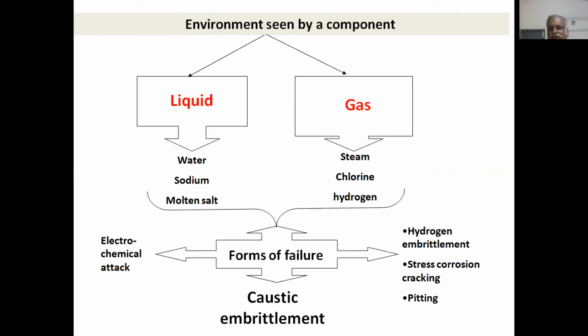The second one is where the solid interacts with liquid and gas, and this is why environment plays a part. In our case, water and sodium, these two are present and travel. When they travel, water travels in the form of steam, and sodium is a hot liquid. How this interacts and what kind of failures occur? One is caustic embrittlement, which is a form of stress corrosion cracking. Several other corrosion modes like stress corrosion cracking, pitting, and hydrogen embrittlement are all possible in our environment. For example, steam, chlorine, and hydrogen are possible.